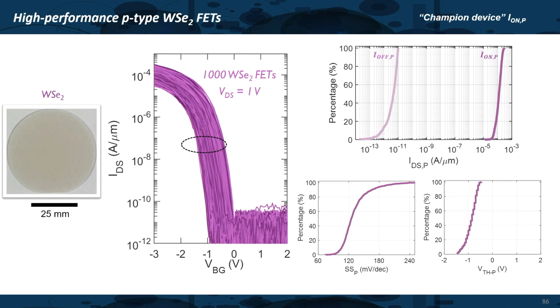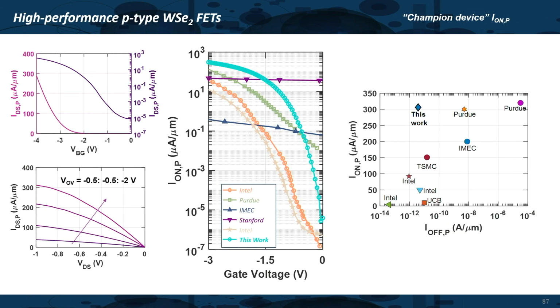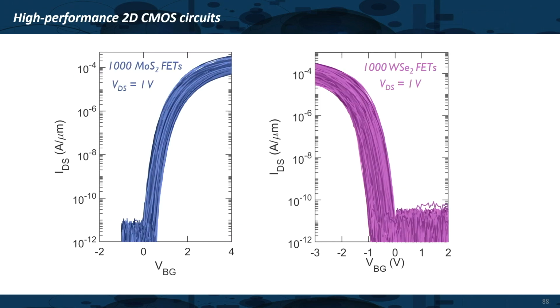And you can see that even the PFETs are off at Vg equal to 0, because that's what I need to make circuits. And again, when you compare it with all the other literature, now you can see that this is probably the best result in literature for the PFET, because we get both very high on current as well as large on/off ratio, right. So now we have both the high performance NMOS and PMOS with the right threshold voltage. So now we can start moving into making more reasonable circuits.